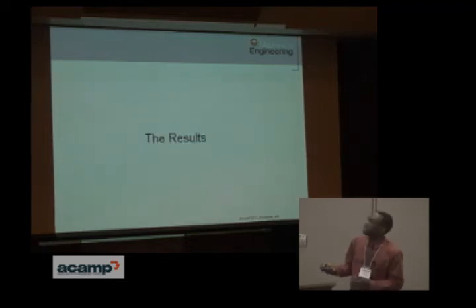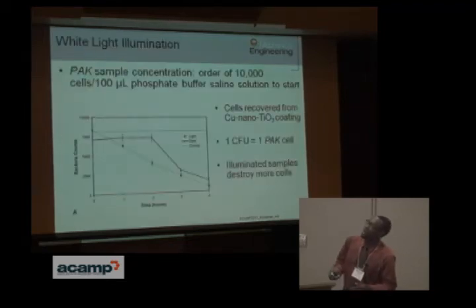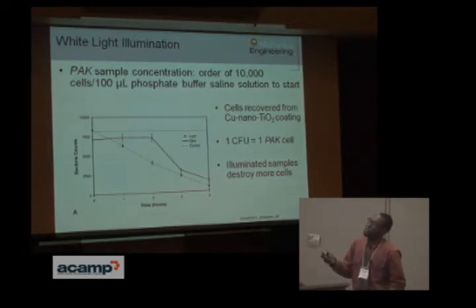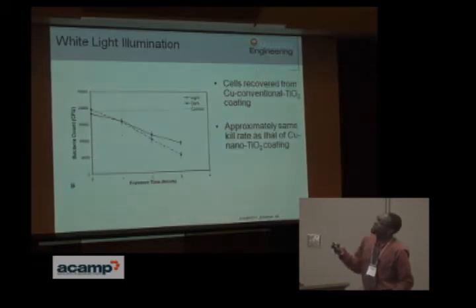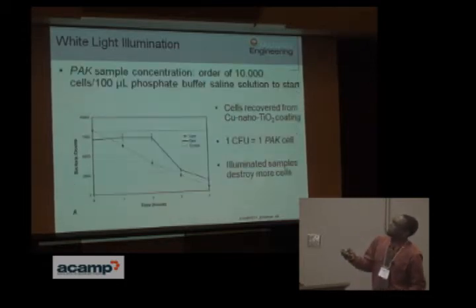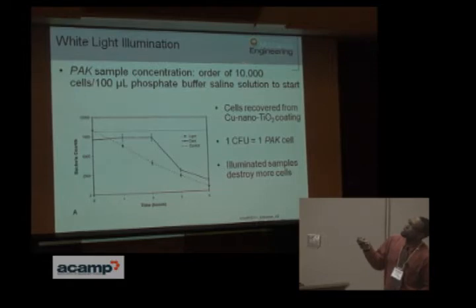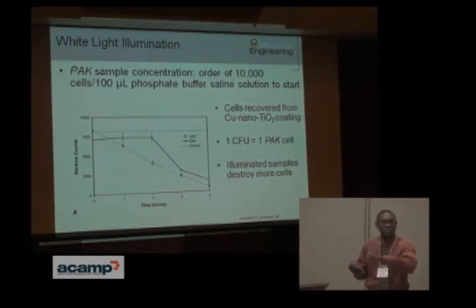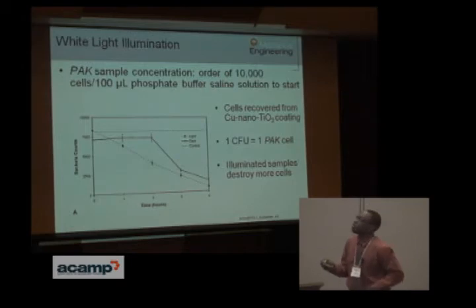So just some of the results very briefly to give you an idea of what we found. All I'm going to show you today are just the results with regards to the white light illumination of our copper titania composite. We have about 10,000 cells per 100 microliter of phosphate buffer saline solution that was put on the surfaces to actually start the process, and then we shone light upon the